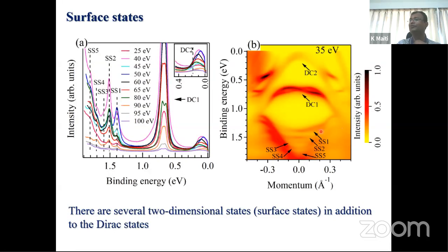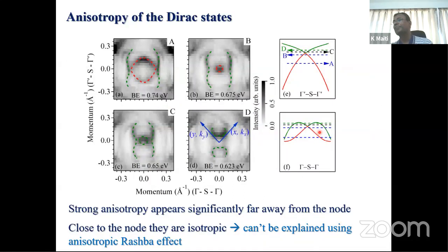Okay. Now let's look at the anisotropy. If you look at these constant energy contours, we have looked at this Dirac node and at different points. Now you see that at this point and this point, they are almost circular. Okay. So there is no anisotropy, but if you go far away from this node, you see there is an anisotropy, like C2 symmetry appears in these constant energy contours.